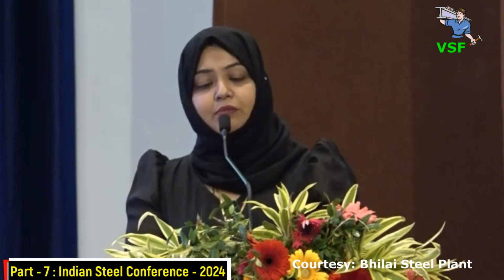It can be used in brick manufacturing with steel slag. The clay-based red ceramics can be replaced by 5% weight of slag and 5% weight of fly ash, giving better microstructural properties, and it will also reduce the sintering process temperature. It can also be used as a high density concrete. Steel slag can also be used in asphalt mixes. The optimal percentage is 40% steel slag as coarse aggregate and 40% of the steel slag as fine aggregate.